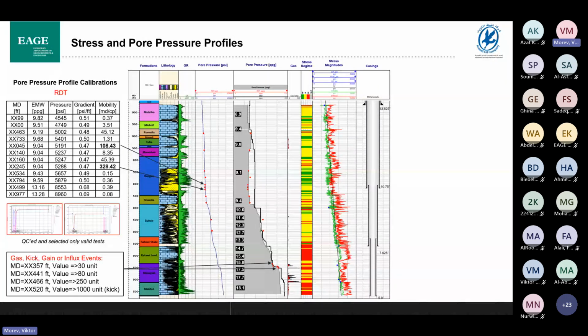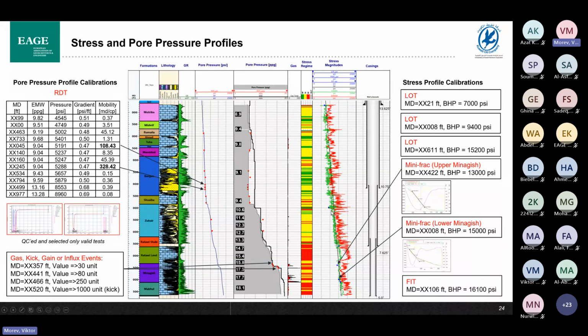Another side of the story is stress profile calibrations. So here on the plot, the black line is the vertical stress, green one is the minimum horizontal stress, and the red one is the maximum horizontal stress. So overburden stress we calculate in pretty simple way, and the minimum horizontal stress we can calibrate to the stress tests. For sure, we can use FIT-LOT, but we don't prefer to do it when we have a mini frac test. So during the mini frac test, we are reaching the point of fracture closure pressure, which is a direct measurement of minimum horizontal stress. So at this particular well, we experienced two mini frac tests in upper Minagish and lower Minagish, and use them for the calibration of the stress profile.